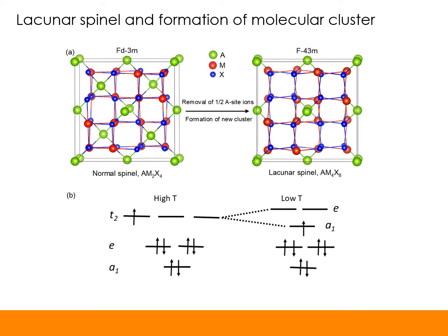In case of GaV4S8, there is a single spin which occupies triplet degenerate T2 molecular orbitals. As a result, this material is highly orbitally active, resulting in orbital ordering at low temperature, below 42 Kelvin. For the orbital ordering, the material elongates along the high symmetry 111 direction. As a result, the triplet degenerate T2 orbital splits into doublet degenerate E and non-degenerate A1 orbitals.